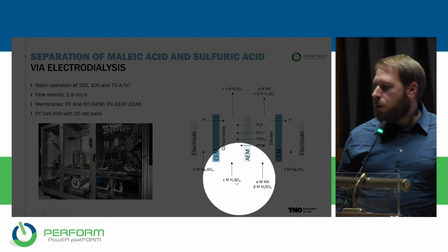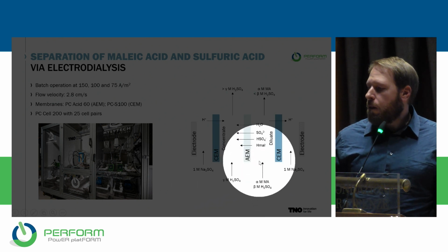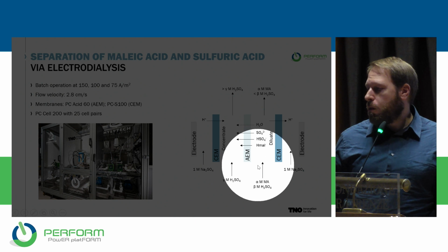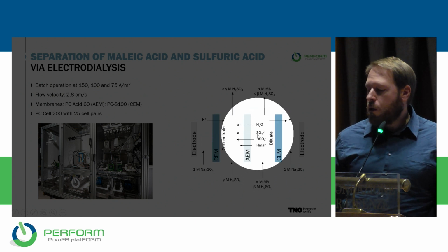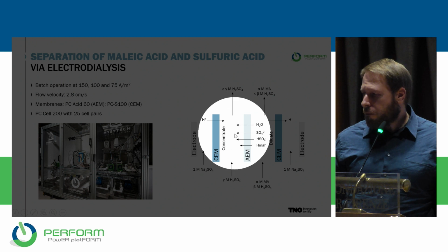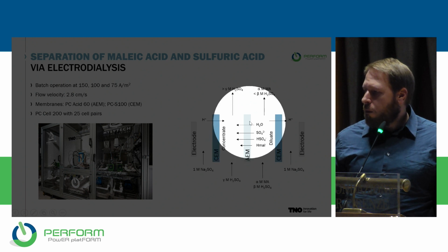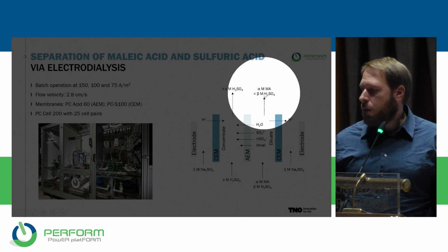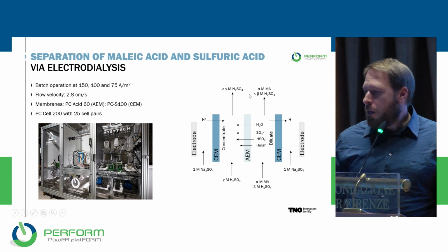So this is the electrodialysis setup that we're using. We feed this maleic acid and sulfuric acid solution on this side, and what we are doing is shifting sulfates or hydrogen sulfates toward the concentrate side, and as a result, in the diluate side, we are only left with maleic acid and a tiny bit of sulfuric acid.